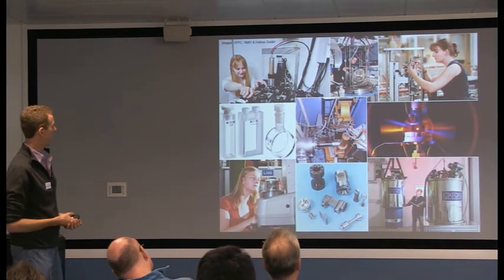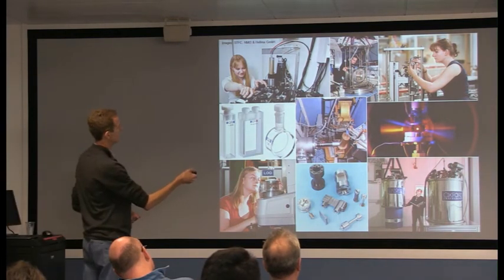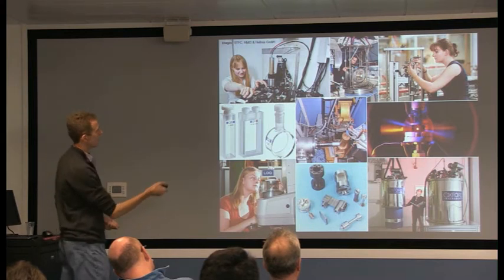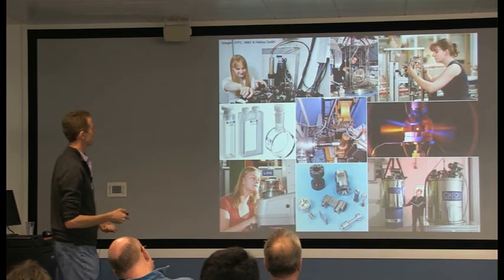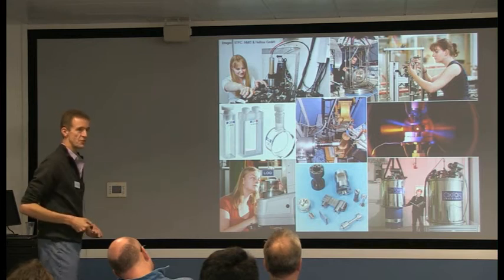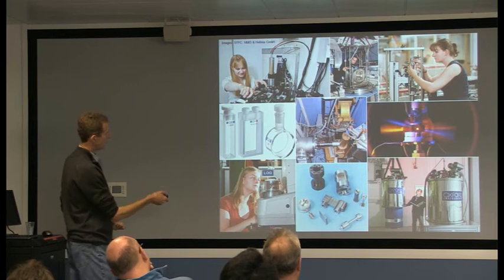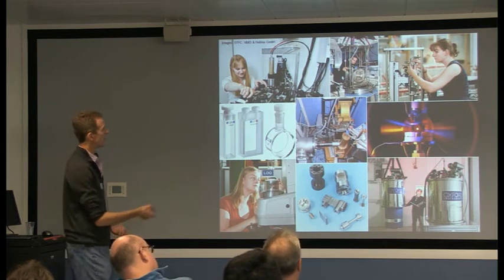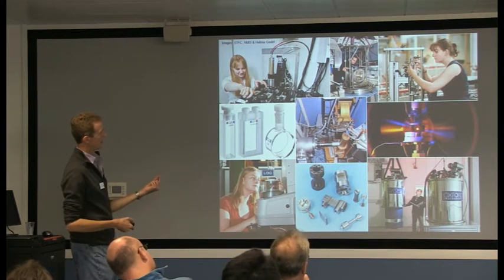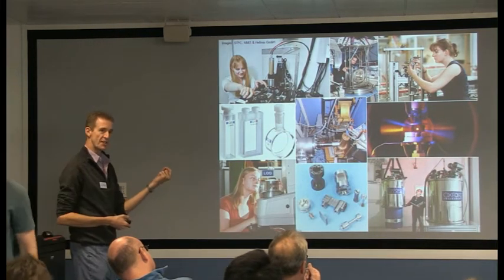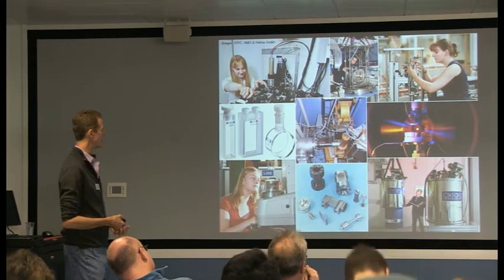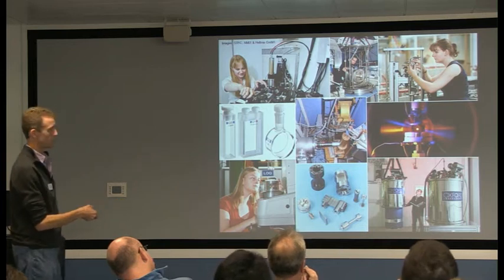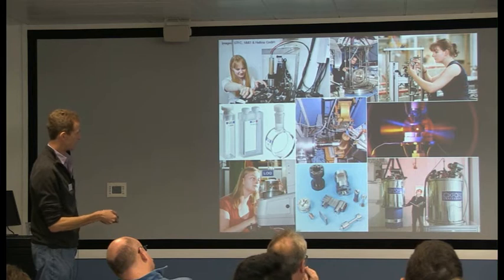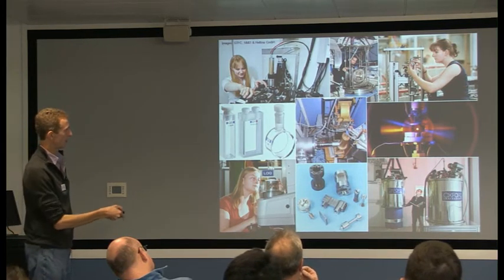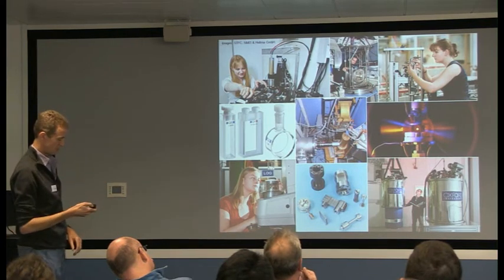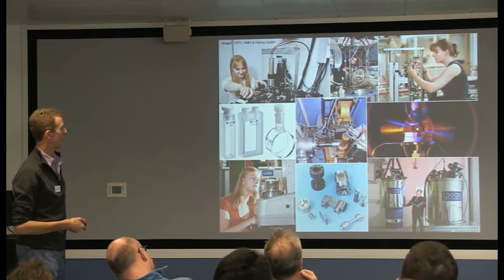This is just a collection of images of some of the different types of sample environment. So we've got diamond anvil cells up there for doing things at high pressure. There's a slightly lower pressure cell there. If you were doing solution work, we typically use quartz cuvettes, just like you might use for UV vis work. I had a user come along and build a microwave reactor down in one of the beam lines. This is laser heating - a pellet of the material is suspended on a gas jet, and then it's being hit with a really powerful infrared laser in order to get it to really high temperatures. We can do things like put commercial benchtop rheometers in the beam line. If you're using furnaces or something like that, then metal cans, for example, and cryomagnets if you're interested in the magnetism. So just a collection of images to give you a feel for the sorts of things that are possible.